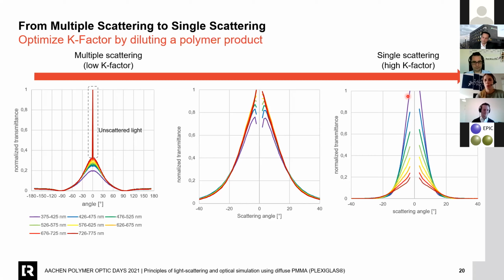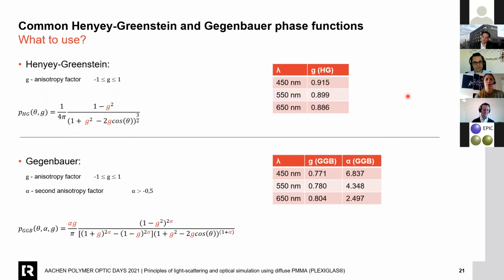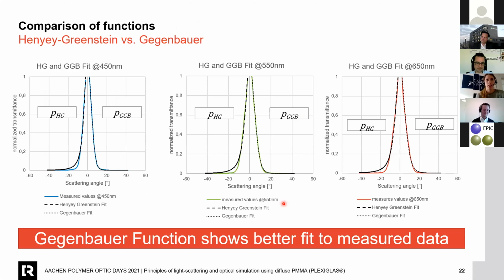So we can use this data for our simulation model, and we fit the mathematical phase functions to it. What kind of phase functions can we use? There's the Henyey-Greenstein phase function, you see the formula there. You have only one variable, the anisotropy factor. The second function you can use is the Gegenbauer function with two variable parameters. On the right, you see the parameters which we calculated after the mathematical fit to our measured data for three wavelengths.